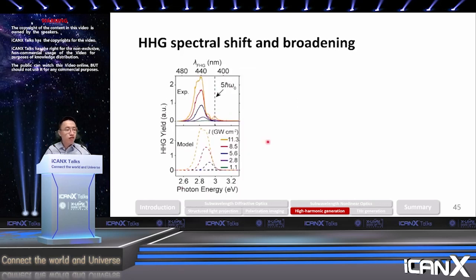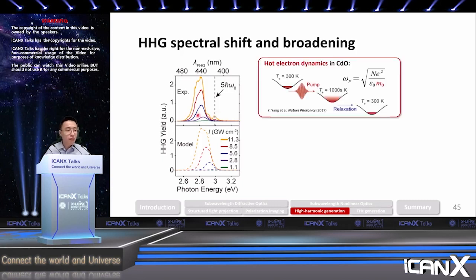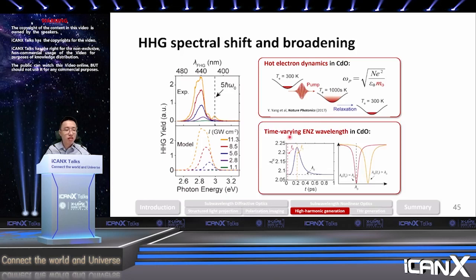And we also found a quite peculiar physical phenomenon: in our high harmonic spectrum we get a very interesting spectral shift and broadening, meaning that in our fifth harmonic signal we are seeing a redshifted harmonic peak as well as a broadened harmonic peak in comparison with a signal which is non-resonant. We explain this shift and broadening of the high harmonic signal using hot electron dynamics in CdO as well as by building this time-varying epsilon-near-zero cavity.